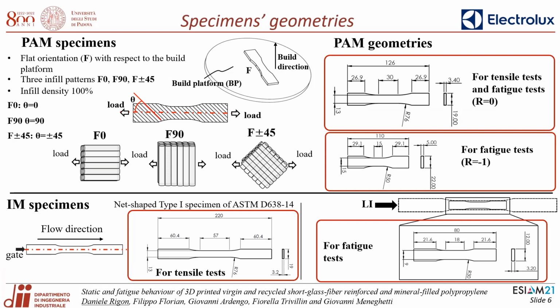The PAM specimens were produced according to this geometry for the tensile test and fatigue test with load ratio equal to 0, while for the fully reversed fatigue test the gauge length was reduced to avoid buckling under compression loads. The specimens were produced in a flat orientation with the three infill patterns indicated by the angle theta that represents the angle between the load and the deposition direction.